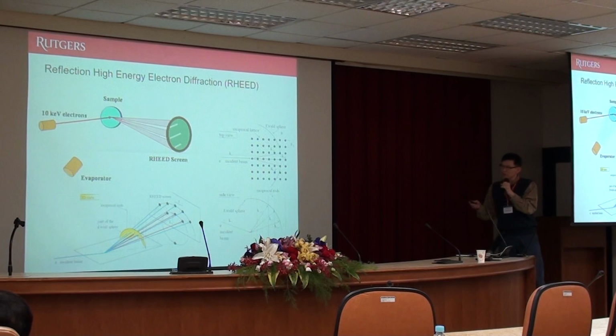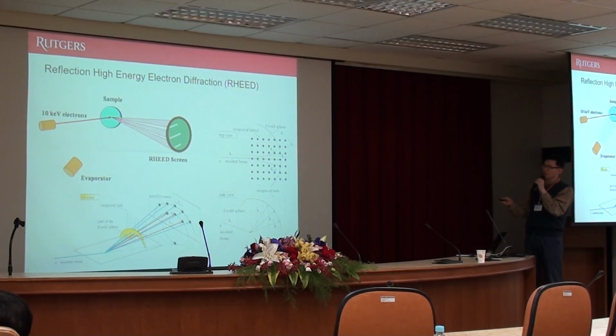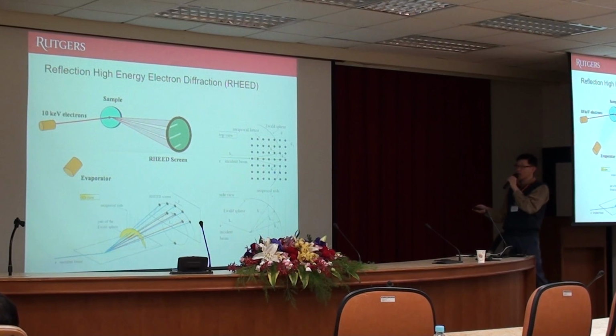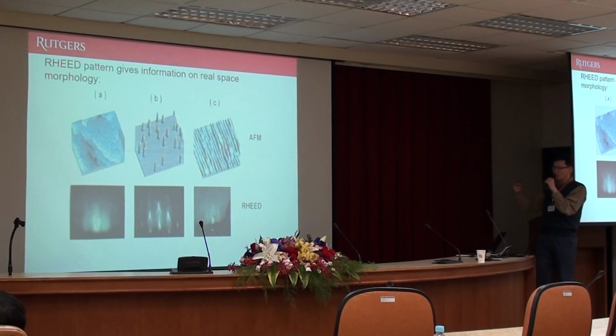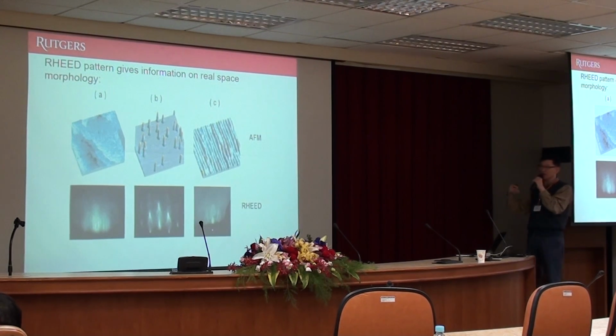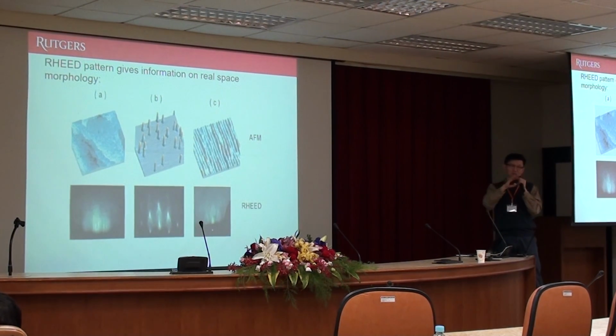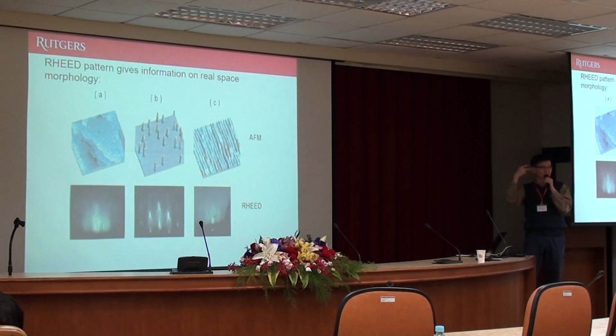In MBE, another important tool is reflection high energy electron diffraction, RHEED. That's a very important tool because you shine a high energy electron beam at a glancing angle and you look at the RHEED pattern. This is the diffraction pattern. By looking at it, you can understand how films grow. So you can monitor the film in real time and judge right away how your film grows. Otherwise, usually in other methods, you just grow it blindly and you characterize the films after you finish the growth. So it takes a really long time to find out if something went wrong.